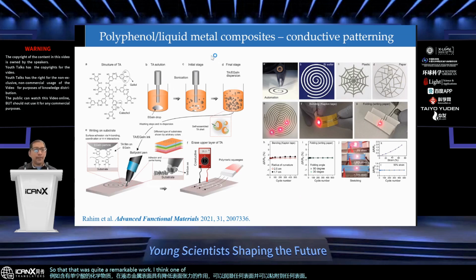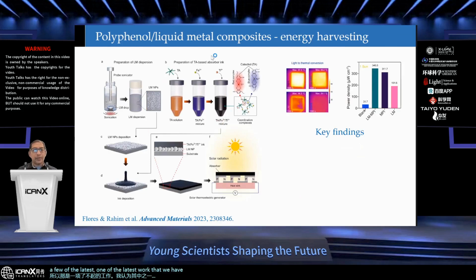I think one of the latest works that we have done is also on a composite. It is a solar thermoelectric generator that we published last year, and it has to do with coordination complexes of natural polyphenol with metal ions that can have a ligand-to-metal charge transfer band. What that means is that, depending on what metal you are using, it can show visible color. For example, with iron, the tannic acid will become pretty black, bluish. And if you are using titanium, for example titanium 4+ ion, then it would look orange reddish.